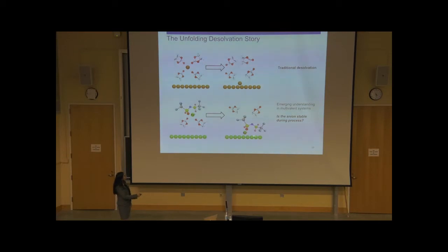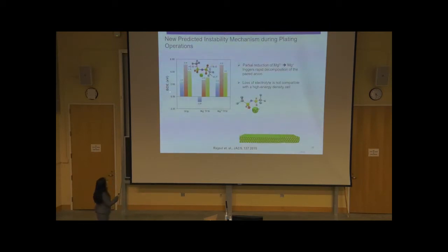And now that we know that the anion acts as a delivery vehicle, it's important to understand if this anion is actually stable during this process. To test the stability of the anion, we computed the bond dissociation energy of this TFSI anion in three different media: the anion by itself, the anion when paired with magnesium 2+, and the anion when paired with reduced transient magnesium 1+. The different colors here represent the different bonds. We found that the anion is very stable by itself. It's also stable when it's paired with magnesium 2+. But the carbon-sulfur bond becomes unstable when it is paired with this reduced transient magnesium 1+.